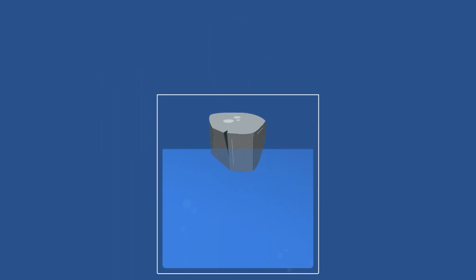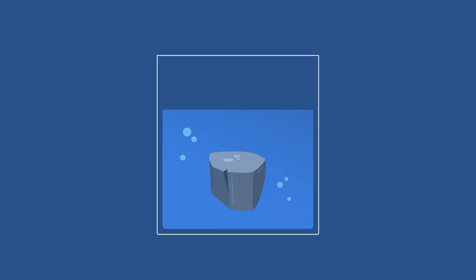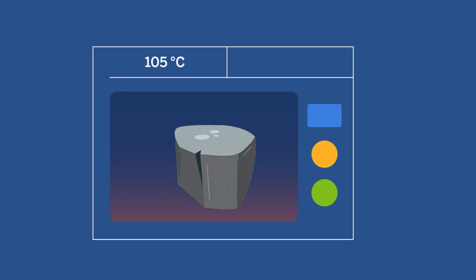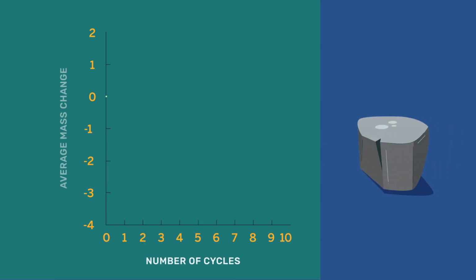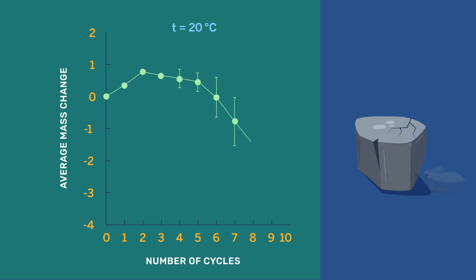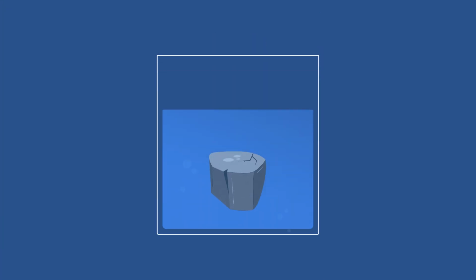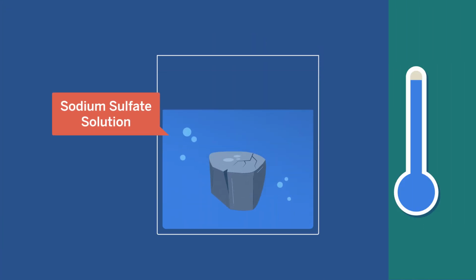It is used in laboratory accelerated testing by using cycles of impregnation in a sodium sulfate solution followed by drying. Mass loss starts after a limited number of cycles and is used as a measure of the susceptibility to salt damage. Damage develops during the wetting phase when the temperature is below 30 degrees Celsius.